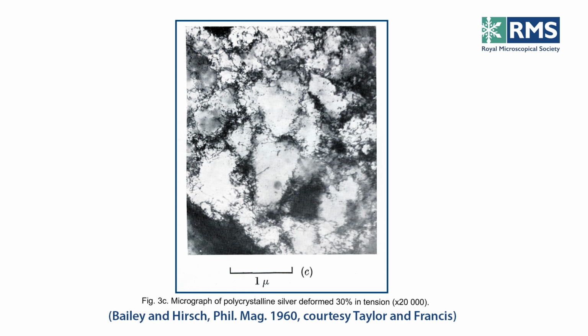This slide shows a micrograph of polycrystalline silver heavily deformed, and you can recognize there are rather indistinct boundaries, but nevertheless you can see that these boundaries are going to be obstacles to further slip across the material, leading to work hardening. You had to increase the stress in order to get any yielding.